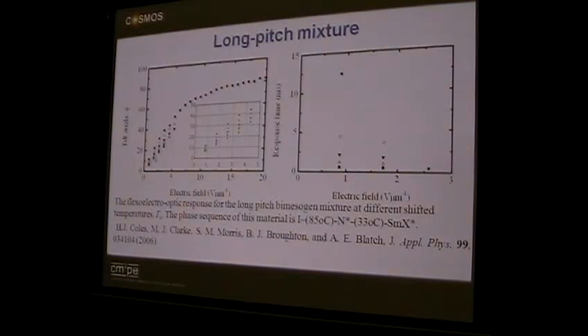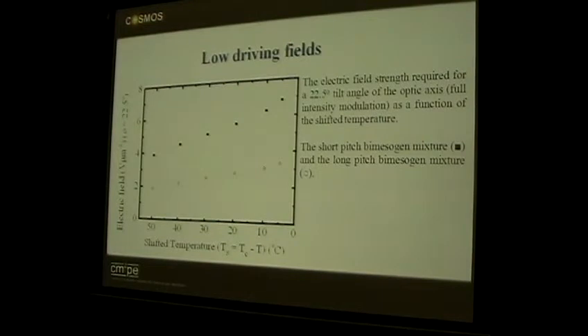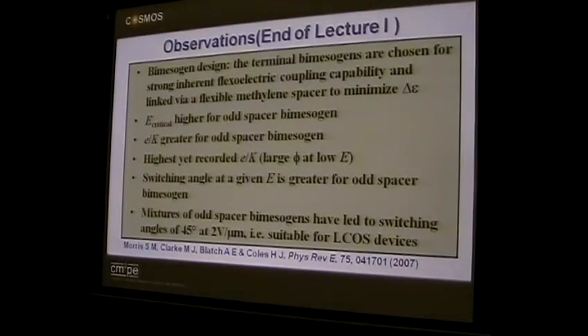For a device, I'm really interested in this kind of range here, 45 degrees tilt. If I had a different host system, 22.5 if it was a normal parameter. And low driving fields, 4-5 volts per micron, depending on the pitch, or 2 volts per micron down here. And that's typical for a display device. If you were talking to display manufacturers, those would be fairly typical driving voltages. So that's where I was going to stop, because I've gone a bit fast, but I can carry on. Is it a good place to stop, where I've caught up?